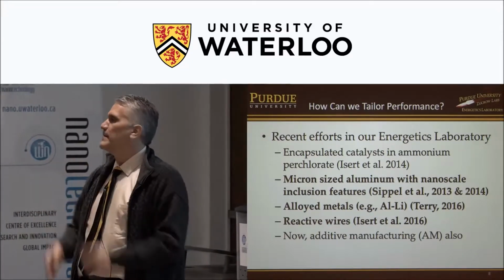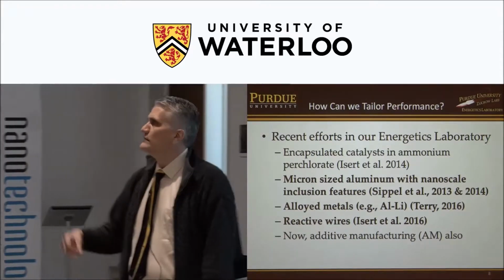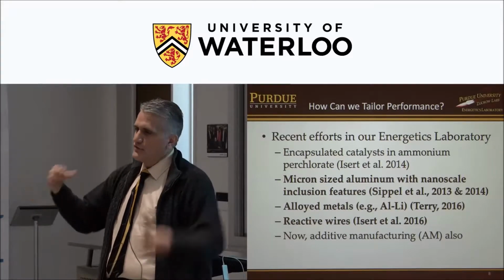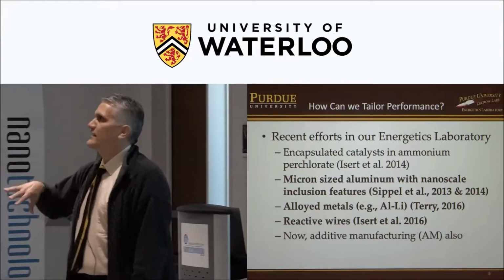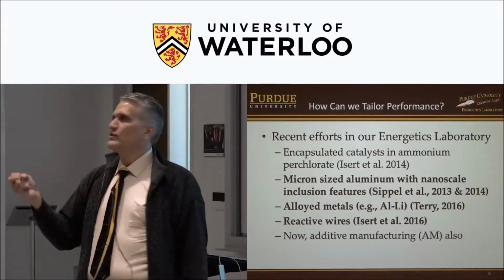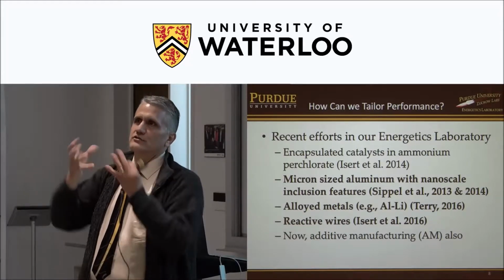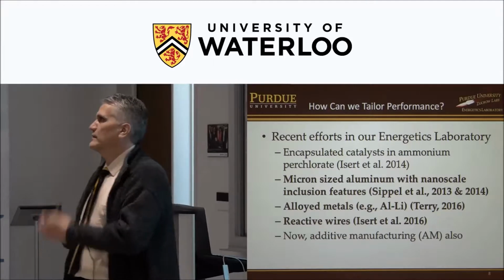We have a solvent that has suspended nano catalysts as well. We have that in our solvent. We dissolve the ammonium perchlorate. We add in an anti-solvent, and those nanoparticles act as nucleation sites for the crystal growth. So the crystals grow around the catalyst.